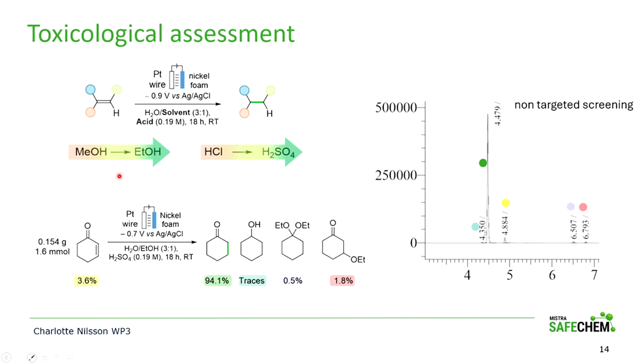So when we were developing this, we discovered early on that instead of using methanol as a solvent, we should change that for ethanol because methanol has intrinsic toxicity. And we were also using hydrochloric acid as the proton source, but we immediately realized that this would produce chlorine, and that has some toxicological concerns, and therefore we replaced that by sulfuric acid.